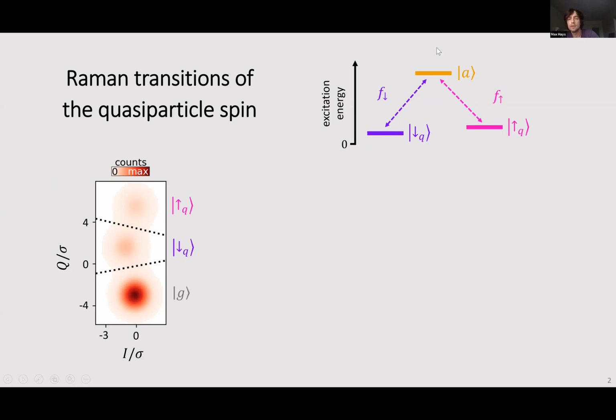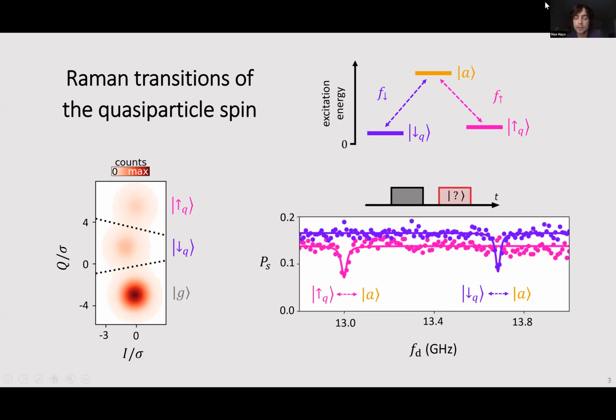So we have this lambda system, and the first step in driving Raman transitions is just locating these two individual frequencies. To do that, we performed a two-tone spectroscopy experiment. Now the y-axis is the probability of finding the system in the two spin states, and the x-axis is the drive frequency of the saturation pulse that we apply before our readout pulse. There are two features: a dip around 13 and a dip around 13.7. The dip at 13 corresponds to driving a quasi-particle out of the spin up state of the lower doublet and into the ancillary state. That's why it's a dip. And the same thing with the dip around 13.7, it's driving a quasi-particle out of the spin down state. So we now have found the two transitions that define our lambda system.